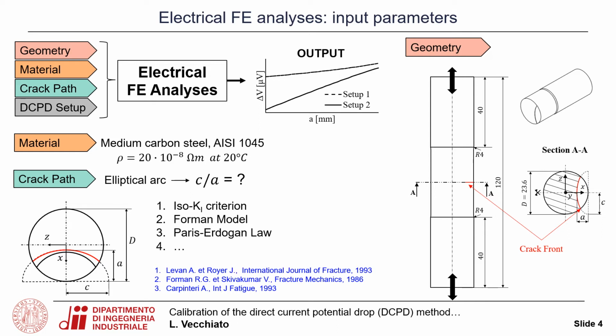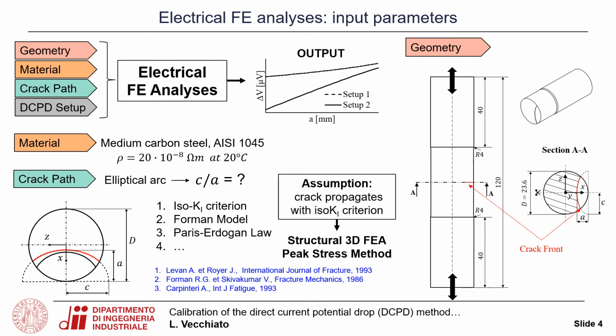In the literature, many criteria have been studied and proposed for studying crack growth for such specimen geometry, and among all, I report the ISO K1 criterion, the Forman model, and a model based on Paris-Erdogan law. Since predicting the crack path is not the aim of this work, but studying the DCPD measure on such specimen, it has been assumed that the crack propagates according to the ISO K1 criterion, and a structural 3D finite element analysis by means of the peak stress method has been performed to define the crack path which satisfies this criterion.